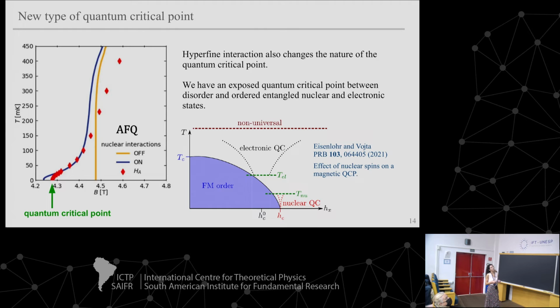This is ferromagnetic order, but their proposal was that as you involve the nuclear degrees of freedom at low temperature, you kind of cancel out the electronic quantum criticality. So you would still perhaps have some signatures of electronic quantum criticality at high temperature, but this would be cut off below some temperature. The original sort of purely electronic quantum critical point would be here, and the nuclear spins or the nuclear degrees of freedom would shift the quantum critical point, and you will have a nuclear quantum criticality with different characteristics here. Now, it's not what we've got here, right? This is not magnetic. The nuclear spins are interacting differently with the quadrupoles compared to the way they would with a ferromagnetic system. And also, you can see the shape of our phase boundary is not the shape of this phase boundary, but it's interesting maybe to explore more what's going on there.